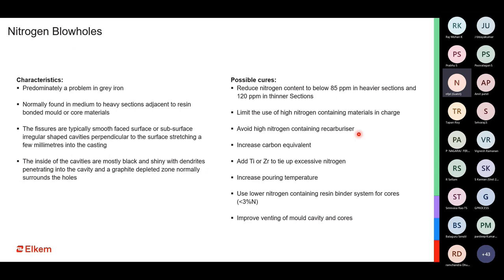Characteristics: it is mostly common in the case of gray iron, and it would be found in the heavier sections. Normally the thin section, small casting, fast solidifying casting does not have nitrogen defects, but the medium to heavy sections which have cores especially, or the resin bonded mold, do have a much higher tendency or propensity for nitrogen blowholes. The fissures are irregularly shaped cavities, mostly perpendicular to the surface, and can go all the way into the casting.